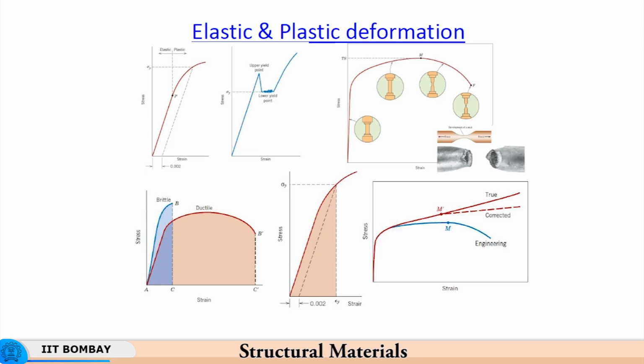Now, as the dislocation density keeps on increasing, there is a point up to which it can increase, thereafter there is no further dislocation density increase. If you look at the rate at which the material work hardens, if you draw tangents to this curve at different locations, you will find that the material is work hardening at a decreasing rate. So, here just after the yield point, the rate of work hardening is very high, but then as the material goes on deforming, the rate of work hardening continues to decrease, and at some point like the ultimate tensile stress,